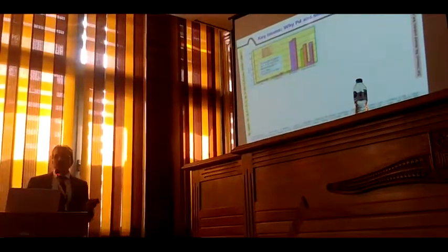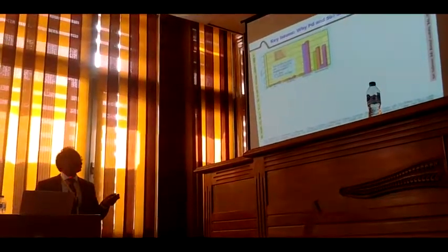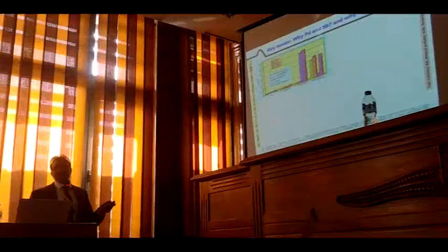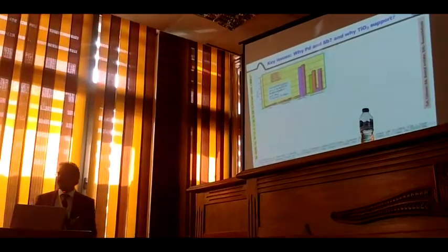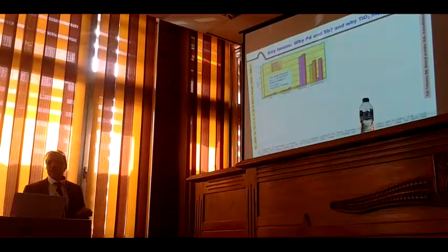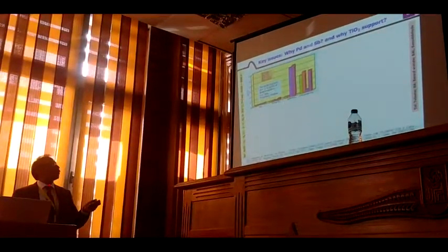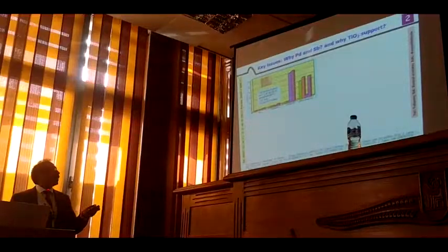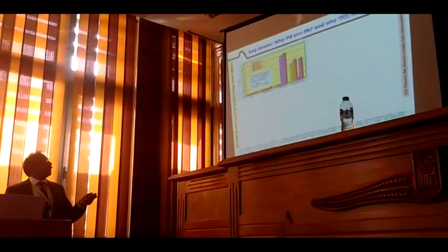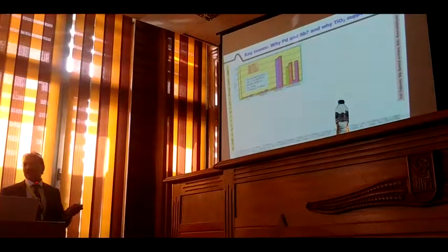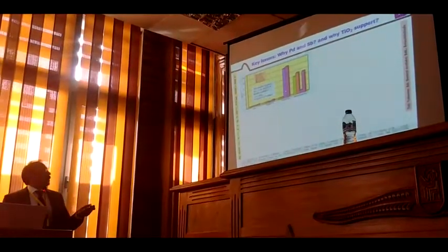If you look at here, when I use pure palladium, pure in the sense monometallic, 5% palladium and titanium, the reaction is going in wrong direction. So the violet one is the conversion of acetic acid, and the blue one is yield of carbon dioxide. We don't want to have carbon dioxide, we're simply burning acetic acid. We want to have vinyl acetate. But when I combine palladium and antimony, you can see the conversion of 2% increases to more than 35%, which is amazing. And the yield of vinyl acetate also increased nearly 30%. Quite surprisingly, astonishingly, the yield of COx drastically reduced from 50% to 5%. This is what we want. So, therefore, we selected palladium antimony composition.